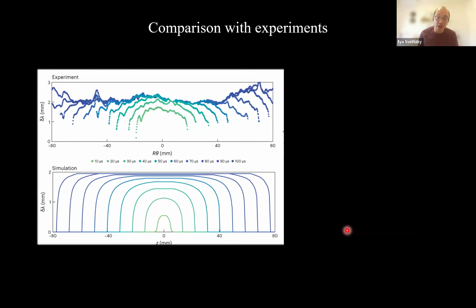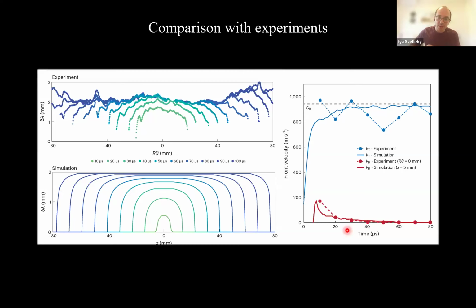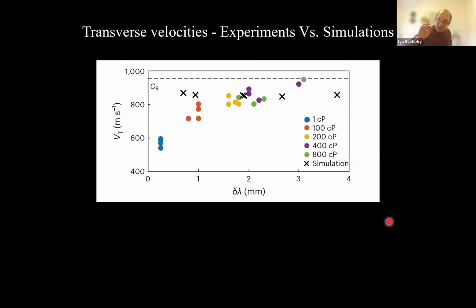We tracked the crack front of the simulation, and I think it looks good. It shows the same phenomenology. The crack jumps at the beginning very rapidly in the radial direction, and then stops and expands both to the right and to the left. And you track the velocities. The solid lines are the simulations. It reproduces well both the tangential velocity and the radial velocity. So this is great. The simulated fracture fronts match the experiments, with a specific caveat that these simulations mimicked very large jump amplitude. So the comparison I showed you happened at about 2 millimeters of jump amplitude.